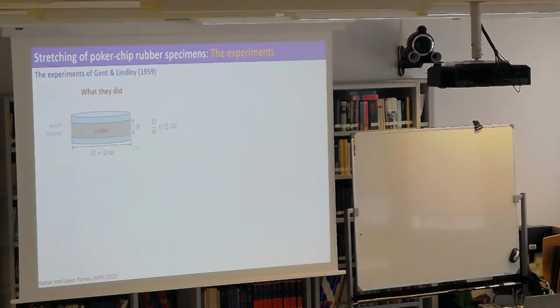And because rubber is essentially incompressible, something is going to happen here. Essentially, when you pull, this is what they did, more or less quasi-statically, for a variety of diameter-to-height ratios. The deformation is really not homogeneous. It's very heterogeneous. And this is what they saw. This is what they did. This is what they observed.